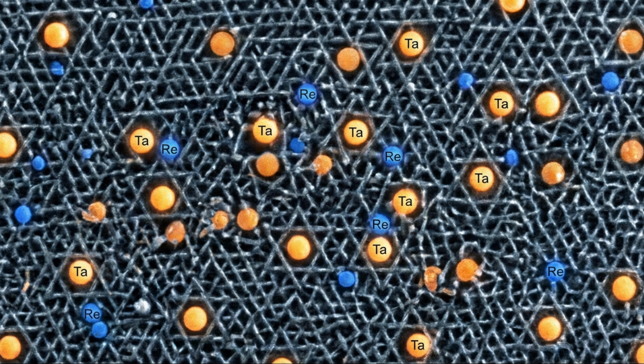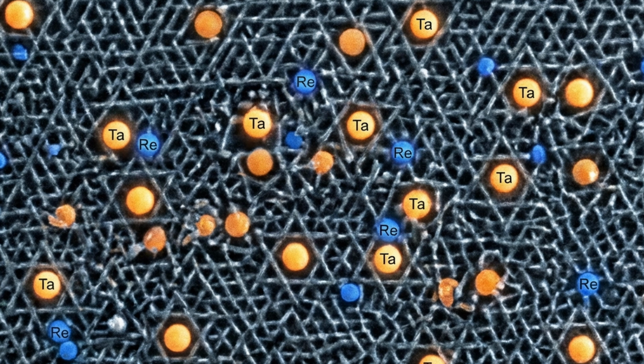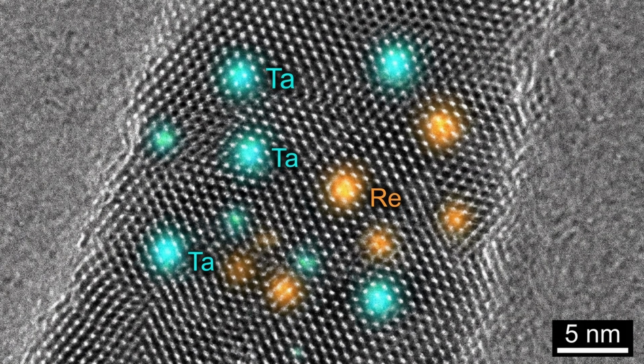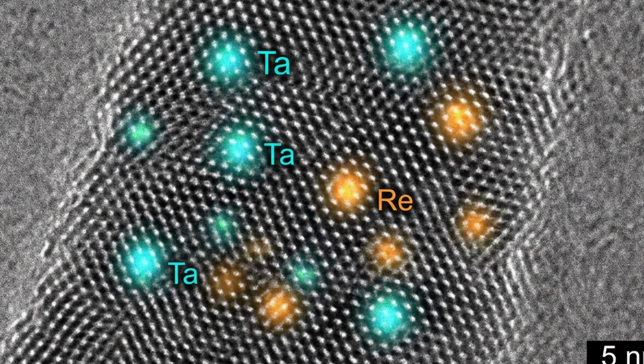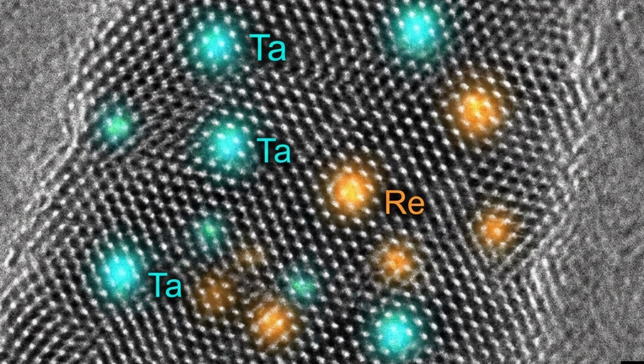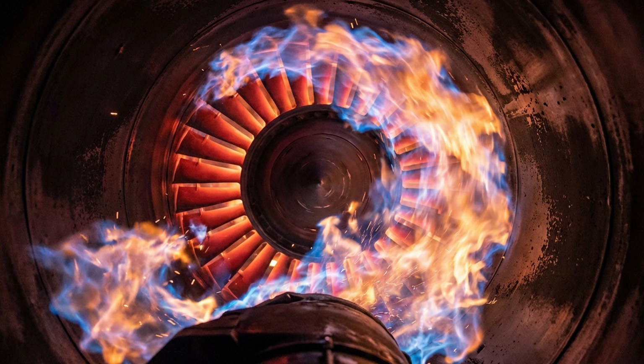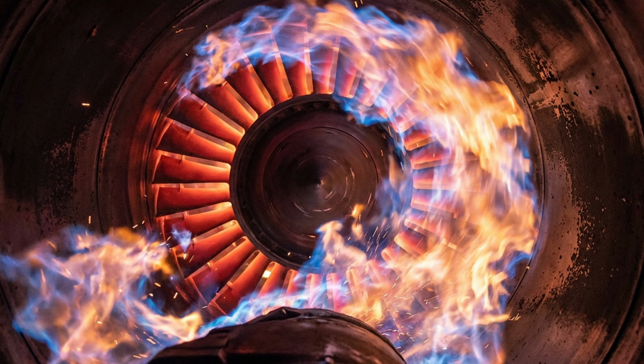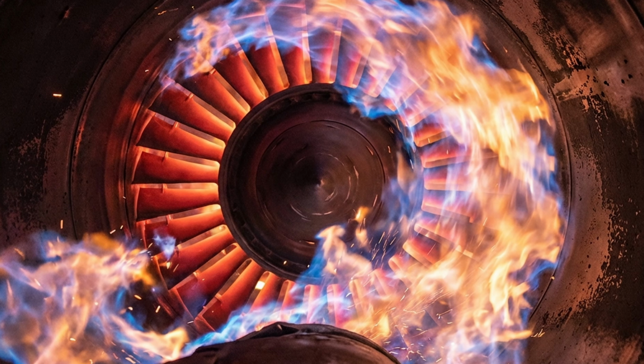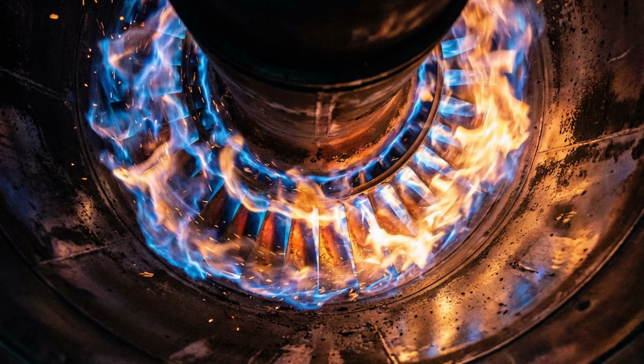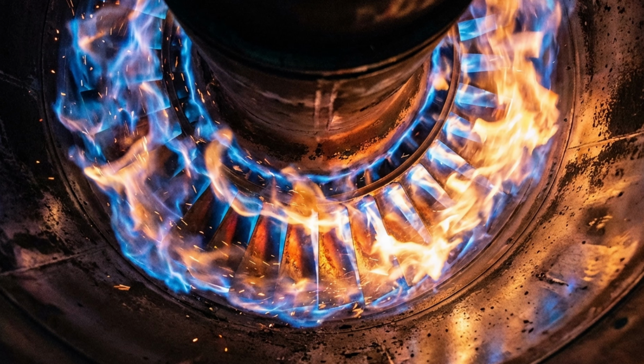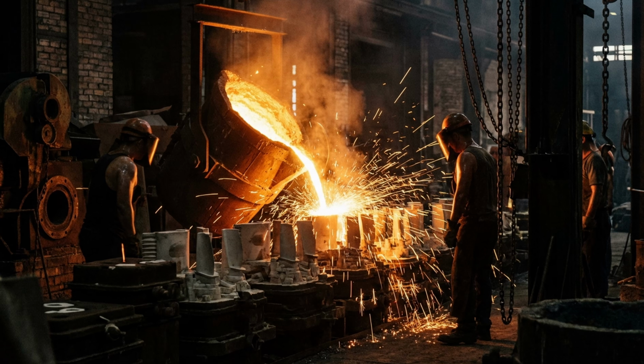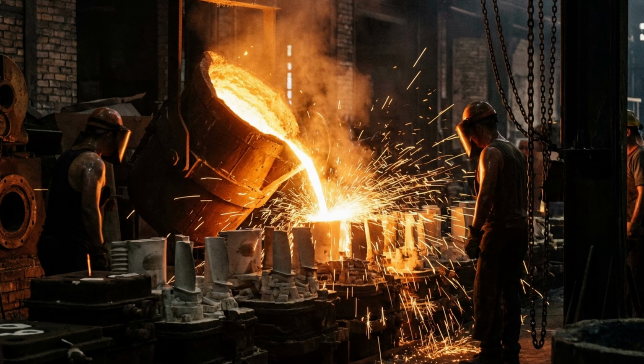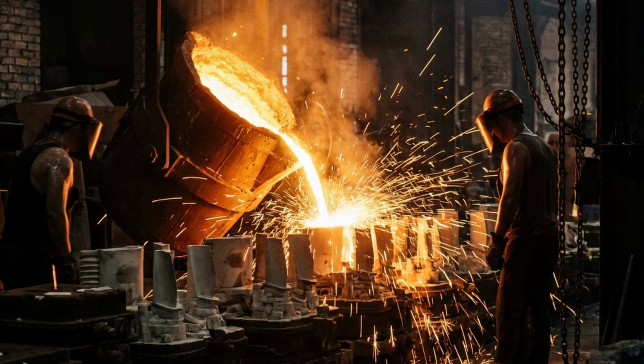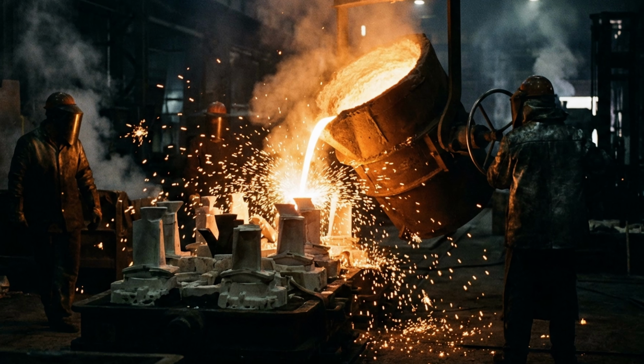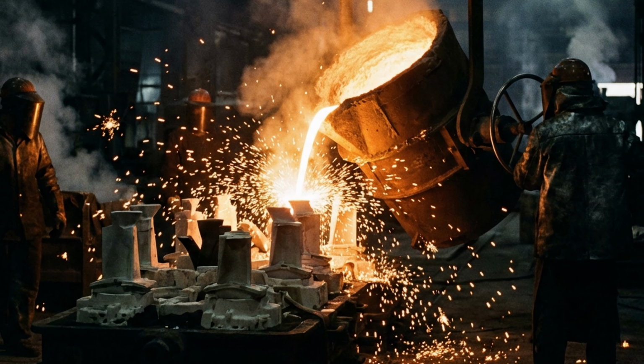Modern generations of these superalloys are heavily doped with refractory elements such as tantalum, tungsten, and rhenium, which drastically enhance their high-temperature mechanical properties, albeit at the expense of inherent oxidation resistance. Because modern turbine blades operate in environments where the surrounding gas temperature regularly exceeds the physical melting point of the base metal by several hundred degrees, raw metallurgy alone is insufficient to prevent catastrophic engine failure. To survive the inferno of the high-pressure turbine while enduring massive centrifugal forces from rotating at over 10,000 revolutions per minute, engineers revolutionized how metals are cast.